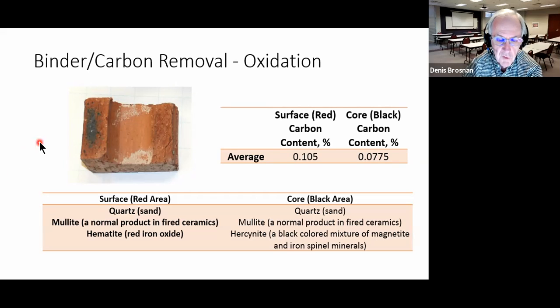Okay. Here's another story. Recently, I was contacted by a guy who bought some bricks in the UK, and he said they're cored, and therefore I don't think they're good. What do you think? Are they good brick or not? And I wrote back and said, any brick that meets your national product standards is what a good brick is. Okay, if these meet national product standards, they're okay. They're a good brick. Now, I further said that very clearly, if you don't see any cracks around the core, okay, if you have cracking around the core, then that could be a bad thing. But if you don't see any cracks on any of the cut surfaces where you see the core, broken surfaces, then the bricks are okay.